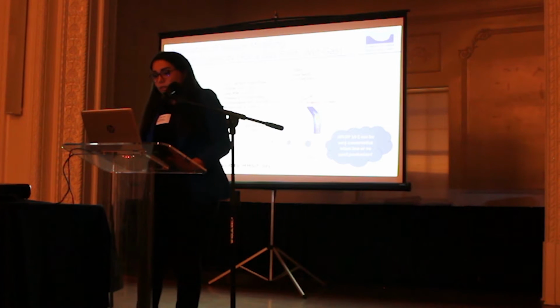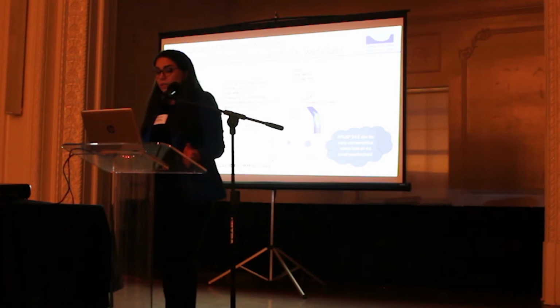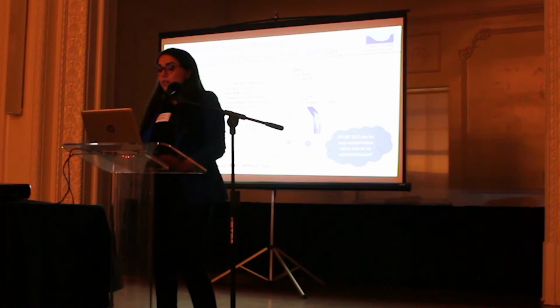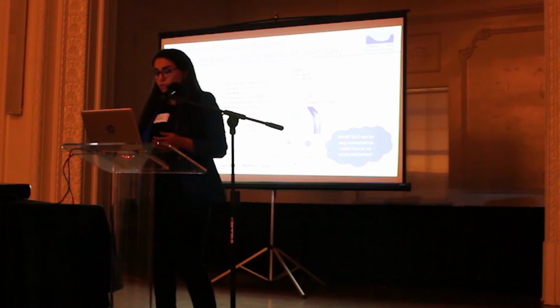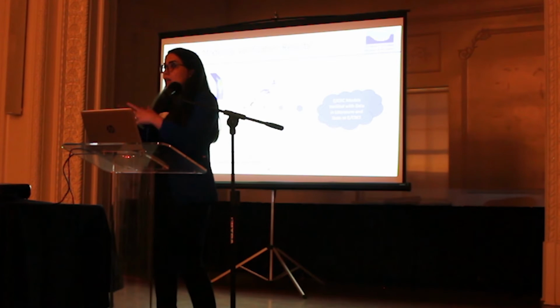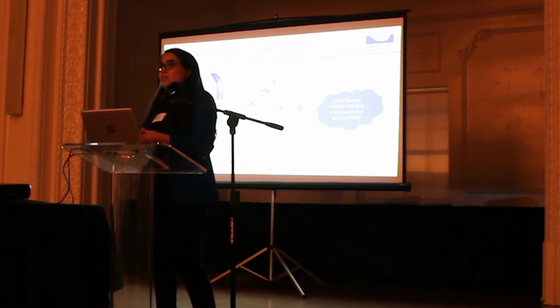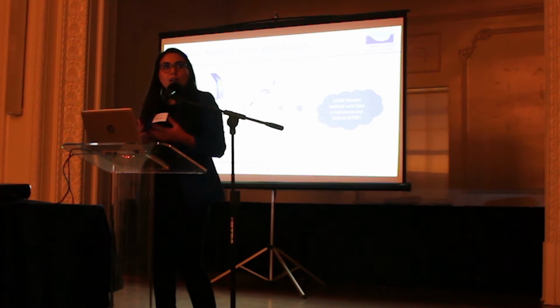The next slide shows the liquid rate versus gas rate. Again, here you see the API model that can be very conservative when low or no sand production is in the system compared to this model that we have for low sand that was developed and validated at Erosion Corrosion Research Center. So all in all, you see that the practice that is available is not doing a good job. It's not taking into account a lot of parameters.